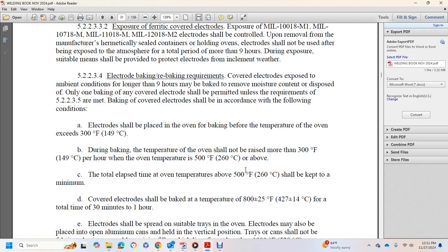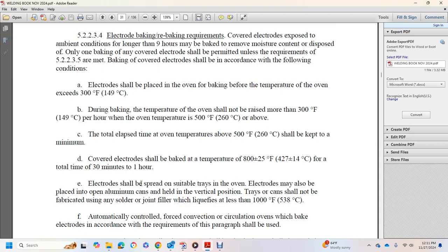The covered electrode shall be baked at a temperature of 800 plus or minus 25 degrees Fahrenheit for a total time of 30 minutes to 1 hour. Electrodes shall be spread on a suitable tray in the oven. Electrodes may also be placed in open aluminum cans held in a vertical position. Trays shall not be fabricated with a solder or joint filler that liquefies at less than 1,000 degrees Fahrenheit. An automatically controlled forced convection circulation oven shall be used to bake the electrodes according to the requirements of the paragraph.